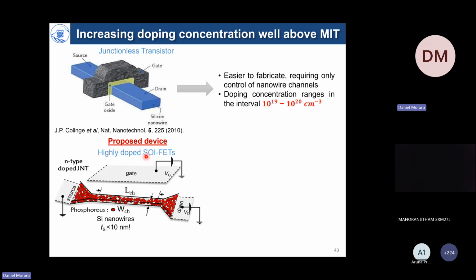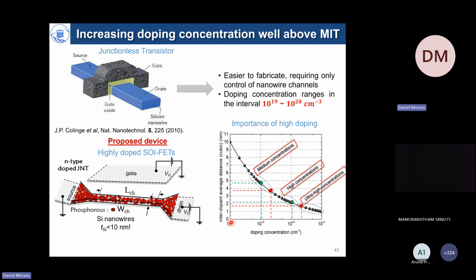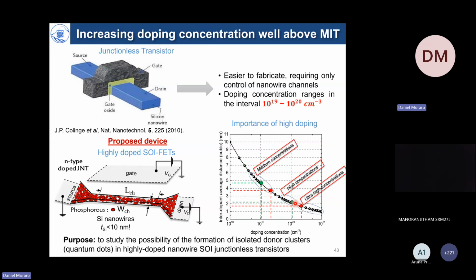So we tried to do a similar thing by creating a nanowire in an SOI wafer, doping very highly, but squeezing the sizes to become, in terms of thickness and width, less than 10 nanometers. If you do that and you tune the doping concentration, which is this horizontal axis, you can leverage the fact that the interdopant average distance, which is plotted from a simple calculation on this vertical axis, can become very, very small. So, for instance, if you choose a 10^20 per cubic centimeter doping concentration, the distance between two dopants becomes on the order of 2 nanometers, just the Bohr radius. So we will have automatically formed molecules in our devices.